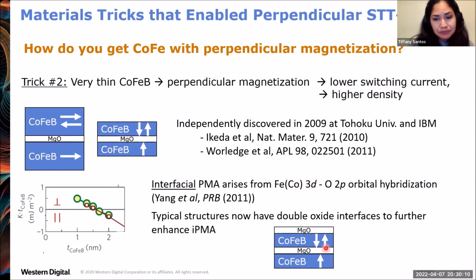And in fact, now conventional free layer structures use an MgO capping layer on top, and then you also have this MgO layer at the bottom. So then you've got these two interfaces generating the interfacial PMA to further enhance the effect.